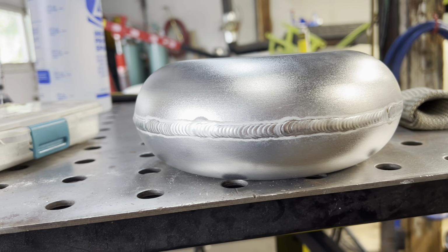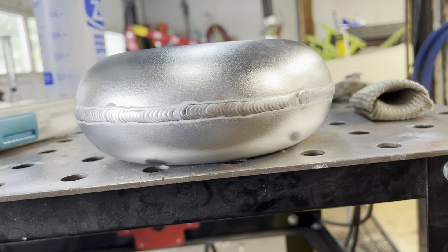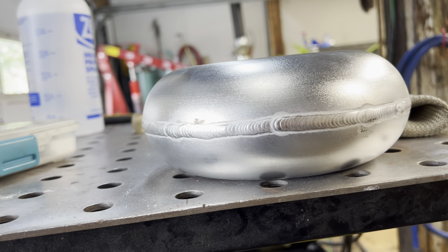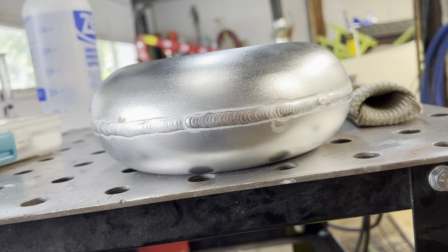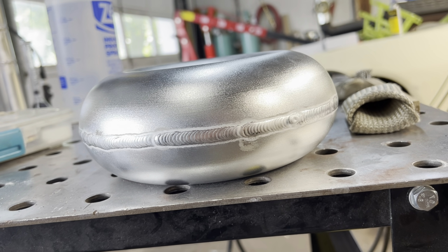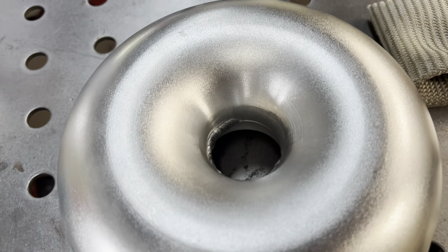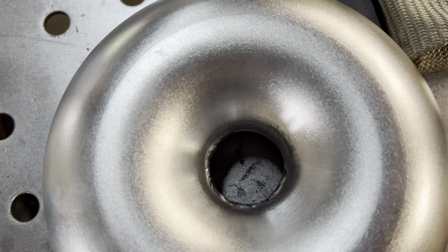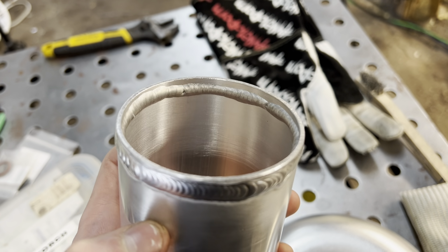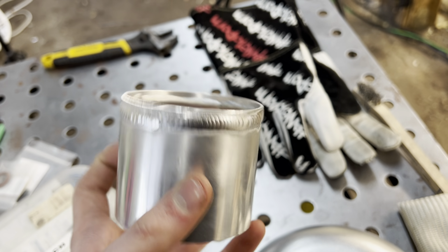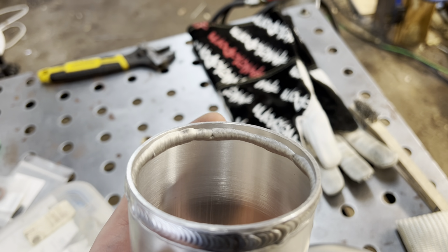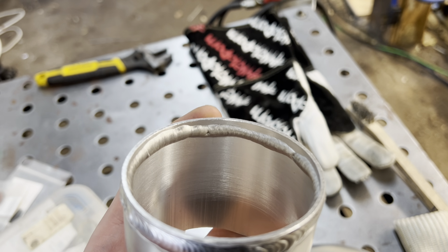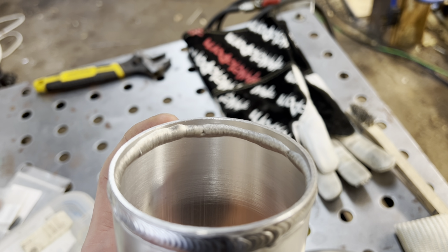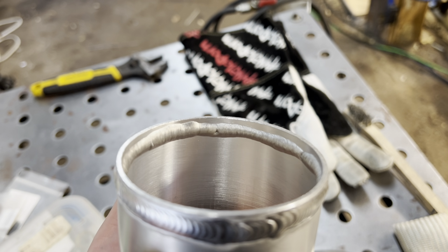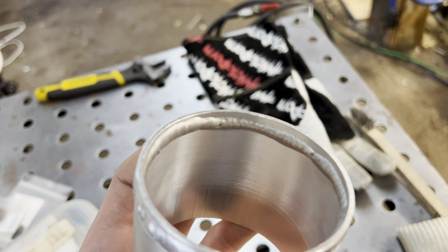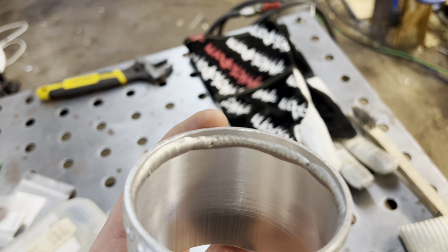The main thing I want you guys to pay attention to on aluminum is that you always have a slight fisheye. As long as it's not a pinhole through to the penetration, it's not to be worried about. And if you do pick up one of these donuts, I recommend not welding the inside until you get them cut apart. It's pretty difficult. I also went ahead and cut up one of our round pieces. You can see here, I made a mistake and didn't penetrate quite enough on the startup of this weld, and I got a slight fisheye on the inside there. That is something you want to try to avoid because that can lead to future cracks.